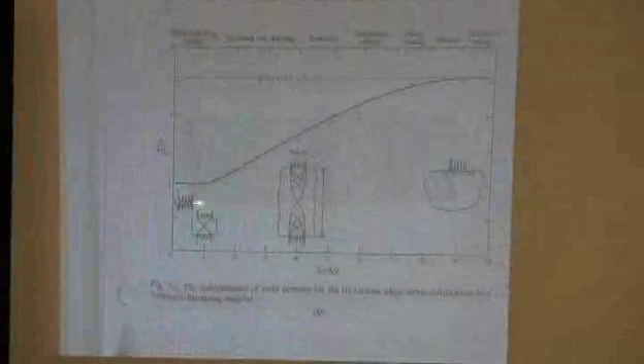And there's an etching technique for a high nitrogen steel that will show you what material has actually started to deform. Okay? And so here's with a little bit of indentation, a little bit more indentation, and a lot more indentation. And you can see, just like Backofen kind of drew on this, you can see the shear lines. The material is actually shearing on those lines. And back here, it shears along straight planes at 45 degrees.